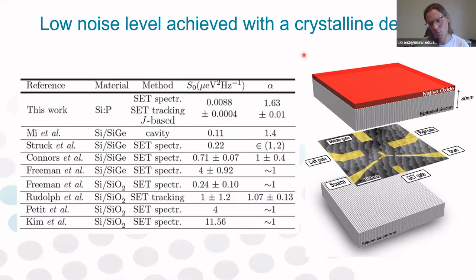We conclude that this is because our device is embedded in a single crystal of silicon with no other foreign material in there, and away from any interfaces and oxides. So definitely, the fact that we have such a low noise level in this device, we attribute to the fact that this device is separated from the oxide by this encapsulation layer.